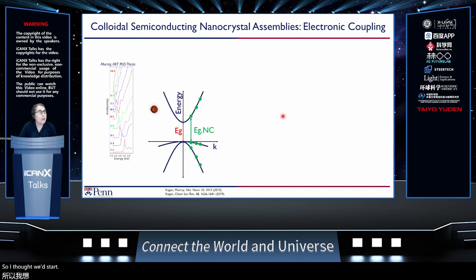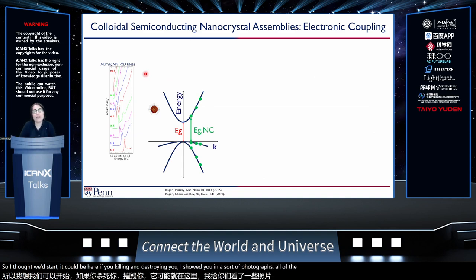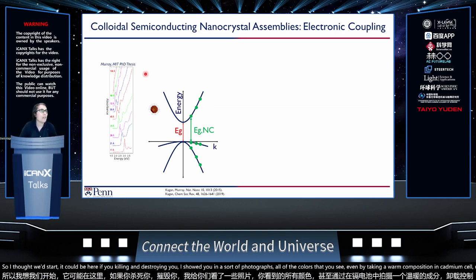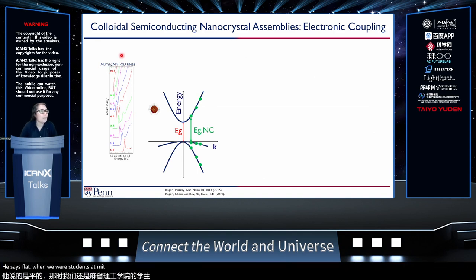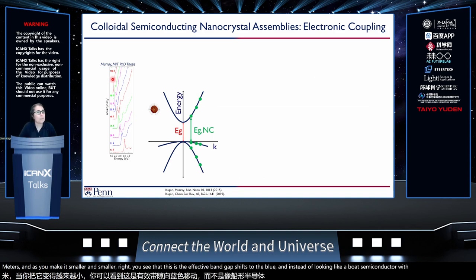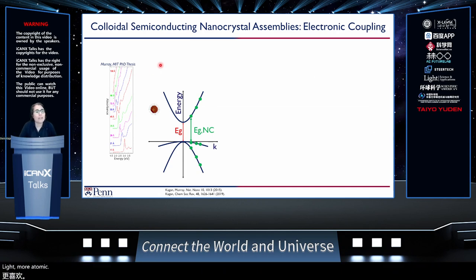I thought I'd start at the beginning by showing you, in a photograph, all of the colors that you see by taking one composition, cadmium selenide, and controlling its size. This is from Chris Murray's thesis back when we were students at MIT. You can really bring together this idea of quantum confinement: when the particle diameter is large, for example, the red here is at 150 angstroms or 15 nanometers. As you make it smaller and smaller, the effective band gap shifts to the blue. Instead of looking like a bulk semiconductor with an onset in its absorption, you start to see these discrete absorption resonances that look much more atomic-like. So sometimes they've been referred to as